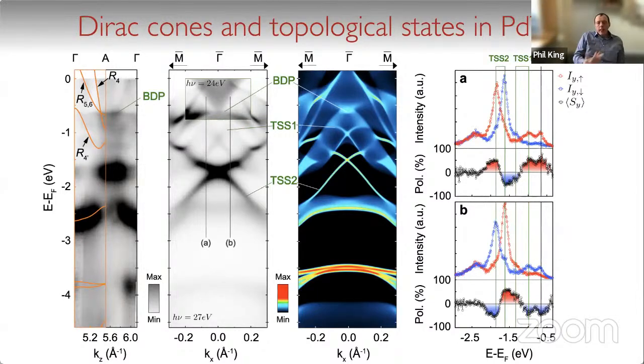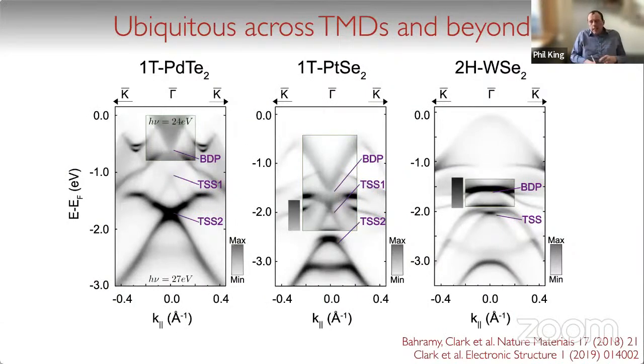And so really starting from a very simple ingredient, just having these p orbitals dispersing as a function of the out-of-plane momentum, we've generated here a ladder of topological surface states and bulk Dirac points in the system. This means that the arguments that go into this are really extremely general. This shouldn't be specific just to palladium ditelluride.